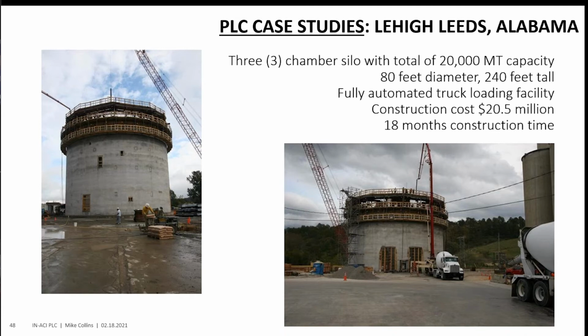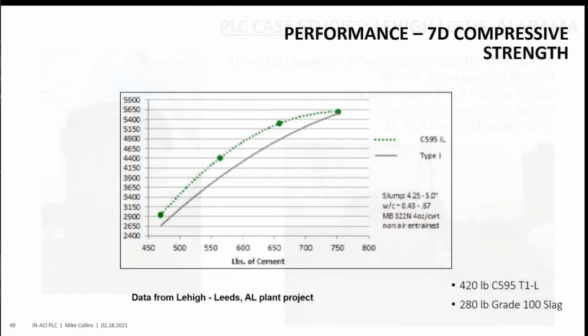This was a slip form project. And the good news here is that this was an opportunity to use PLC, not only just PLC, but it was a PLC slag combination for durability. And so here's how some of the data turned out. When we look at the C595 data, you saw that at different cement contents, that the 595 data exceeded the type 1 performance. And again, this was 420 pounds of type 1L with 280 pounds of grade 100 slag.